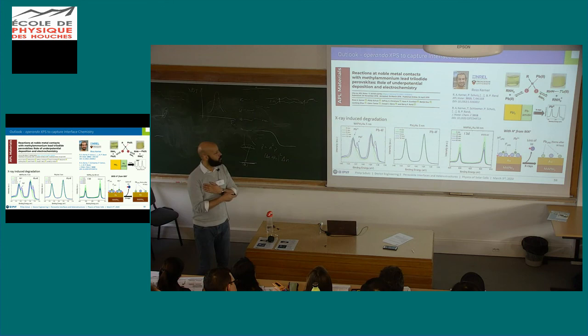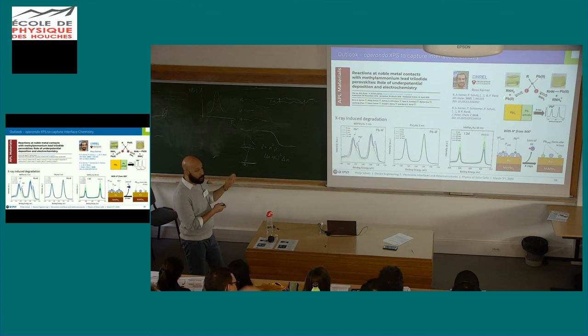So if you're in the perovskite, you have lead in a 2+ state, and you have oftentimes amines that are not completely reacted in the perovskite structure. Now, these amines can form a very loose bond with the lead, but if you have a second amine coming into this equation, it can catalyze, take away or deprotonate this compound, leading to this lead amide component, which is very sensitive to X-ray radiation and will eventually break apart. And you are also left with ammonium, which is also very volatile and will go into vacuum.